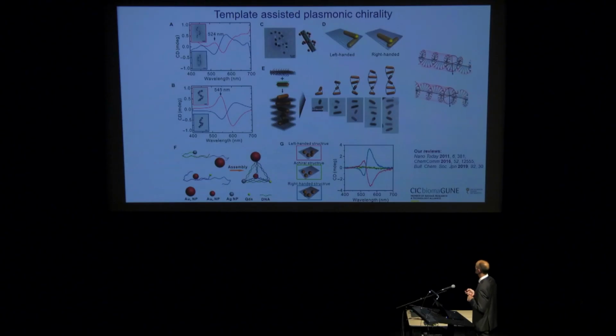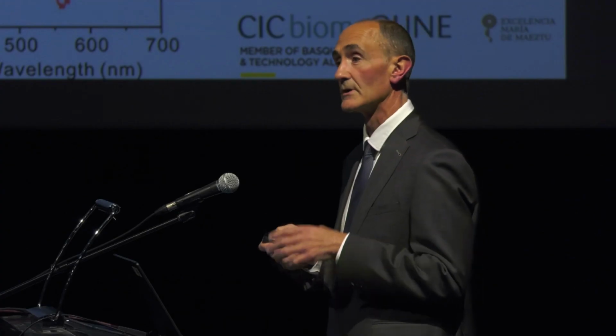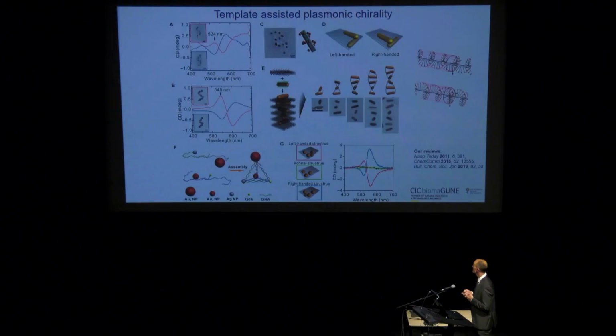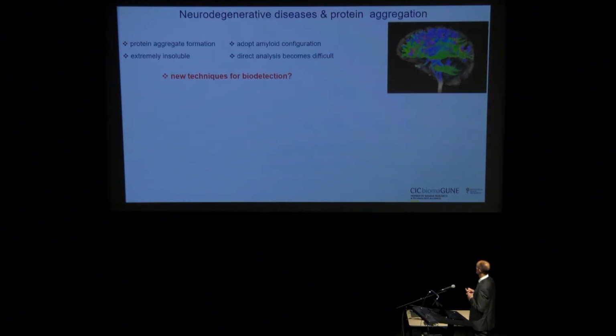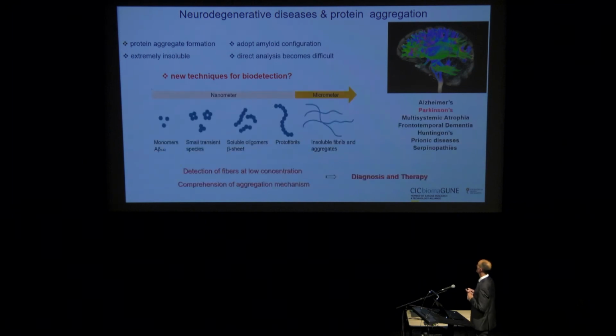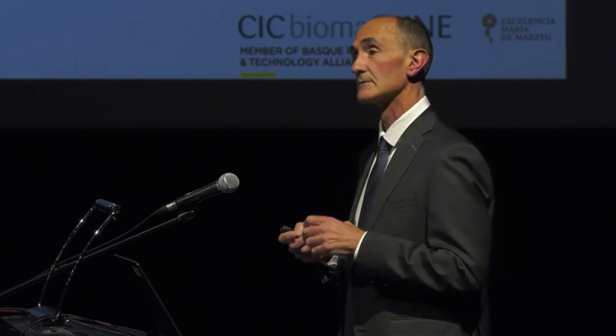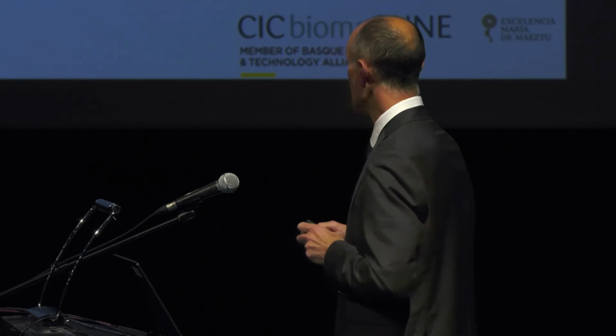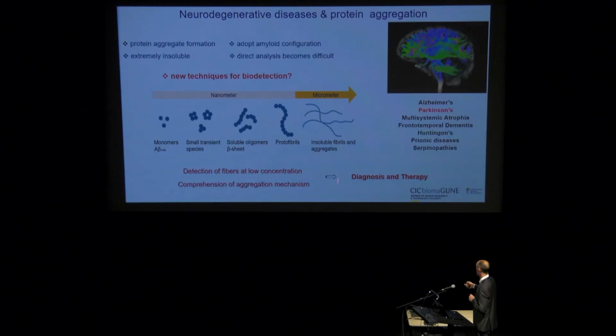And so this has been done in the literature in many different ways, mostly using DNA or DNA origami, which is very interesting, and you can obtain model systems, but it's not very practical. What we proposed a few years ago was that by working with amyloid fibers, we would at the same time have the perfect templates to organize gold nanoparticles into chiral arrays, helical arrays, and we might find a way to help diagnosing very important diseases, as all the neurodegenerative diseases listed here.